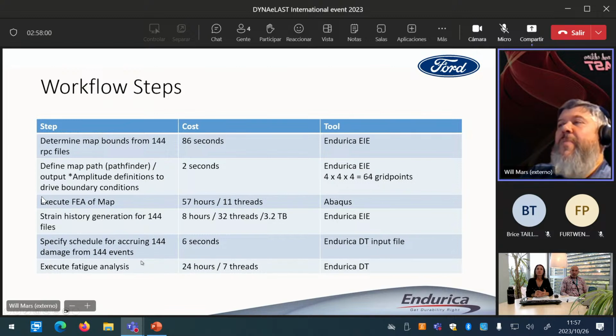So bottom line, this is the workflow costs for this particular problem. To define the map took about 1.5 minutes. To build the map took us about 57 hours of Abaqus. To run the EIE strain history interpolation took us about 8 hours, running on 32 threads. That produced a file that was 3.2 terabytes. So when you run these problems, you're going to need a large amount of disk space. And then finally, to run the damage analysis, that job to process the 3 terabyte stress strain file took about a day, running in parallel on 7 threads with DT.